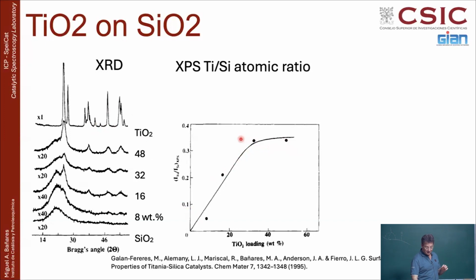So somehow the titanium to silica ratio appears to level off as you increase titanium content, because that one is no longer apparent to the XPS, because you are starting to make a 3D structure of titanium. And that is basically corresponding to these values around 30 plus, 40, 40 plus, which is where you start to clearly see the diffraction pattern of X-ray diffraction.